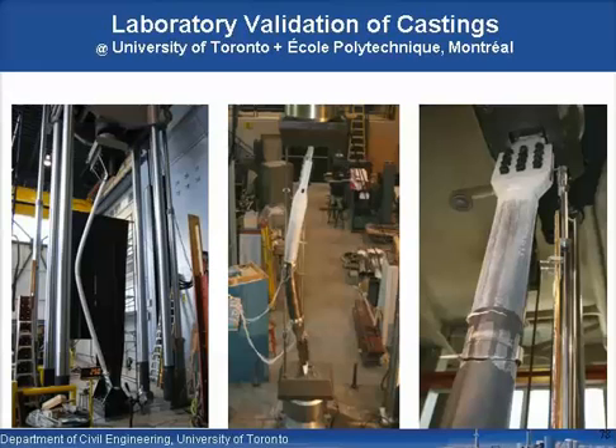and then on these tests on the right-hand side here, where you see we've got a more punishing situation with a lower KL over R deliberately, we've actually yielded the tube in tension here, and all the whitewash has come off here during a tension loading cycle, but you'll notice that the whitewash has not flaked off here around the actual connection because it's actually remained elastic, which is the aim of the game. So hinges occur in the gusset plate up here, and in the middle of the tube, and in the gusset plate down the bottom as well. So you have a sort of an instant problem solved for you.